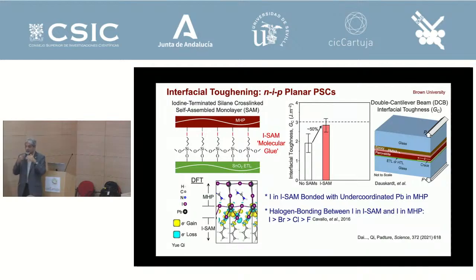So you get both effects, right? And so what happens is the halogen bonding actually decreases as you go to a different halogen. So for example, if you use bromine, then the toughness goes down. And when you terminate it with hydrogen, then it becomes almost like there are no SAMs there if you terminate it without the halogen, right? Anyway, by putting the SAMs in there, the SAMs also don't kill the properties of the solar cell. It actually makes it better.